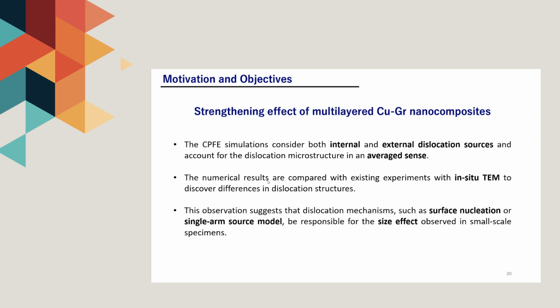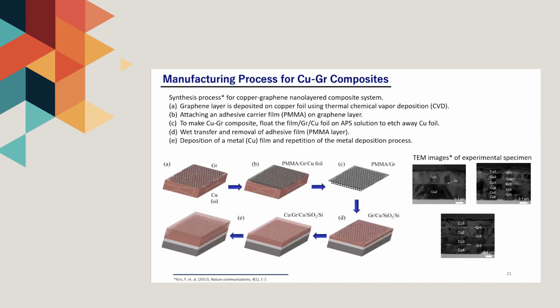The numerical results are compared with the existing experiments that you will see in a minute with in situ TEM to discover differences in dislocation structures. The observation suggests that dislocation mechanisms such as surface nucleation or single arm model be responsible for the size effect observed in small scale specimens.